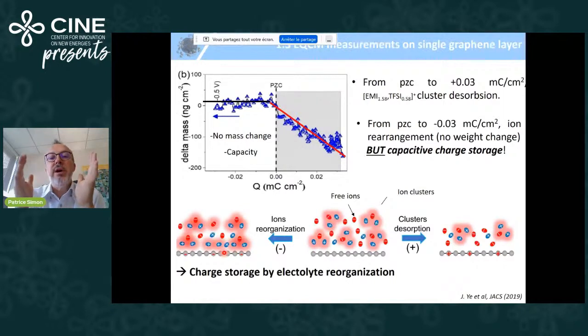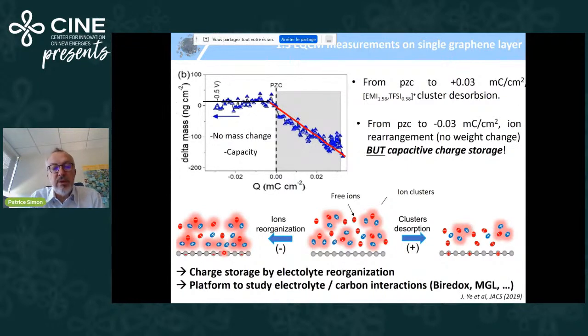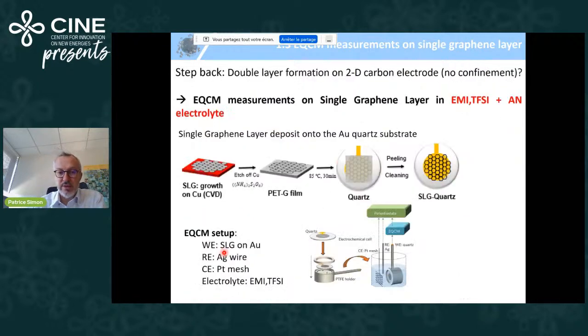Modelization told us that in fact, when you inject negative charge onto the graphene, your EMI+ cations can change their orientation from a vertical orientation to the carbon surface to a parallel orientation to the carbon surface when you increase the negative charge density. And this is a very interesting result because it shows that you can store the charge by simple electrolyte ion reorganization. No need to have a flux of ions. So beyond these interesting results, it shows that single-layer graphene, EQCM, electrolyte can be used as a platform to study the electrolyte-carbon interactions. And this is what we continue to do recently.